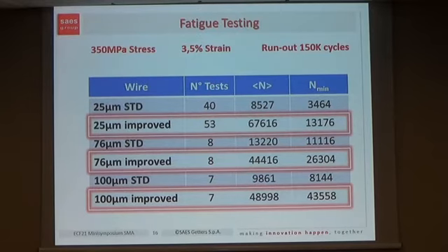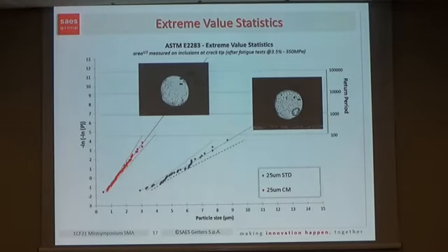standard materials. But by changing the conditions, so in less aggressive conditions, we observe an improvement of the fatigue life of over 100 times for these low inclusion wires. So we also checked the fracture surface of all the failed wires, just to apply again on this material our extreme value statistics. And this is clear also in this case. The distribution of extreme inclusions is completely different. We move to a very, very low inclusion size in the improved wires. So we are almost always below 3 microns at the crack tip in terms of max inclusions observed.